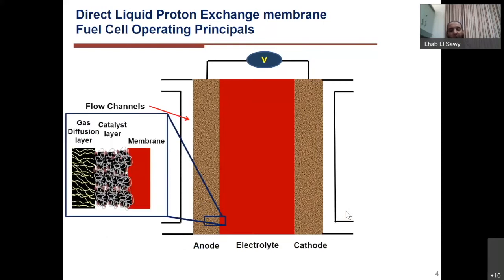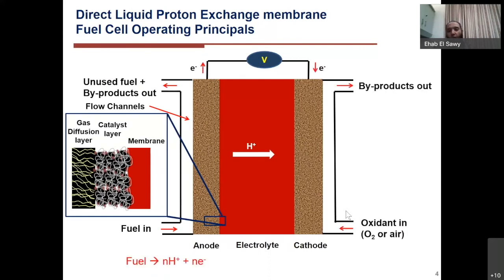So we have the fuel that's going in to the anode side, where the fuel is oxidized at the catalyst layer that's composed of gas diffusion layer and the catalyst layer. And then the proton moves through the membrane, going to the other side where the oxygen is reduced and gives you water as a product. And this is the complete reaction that's going on.